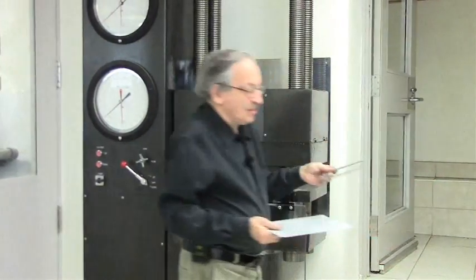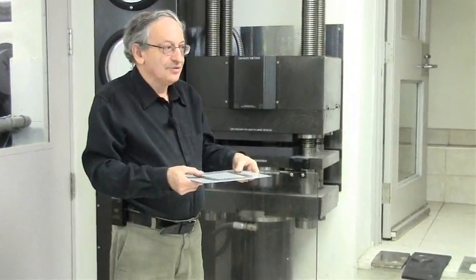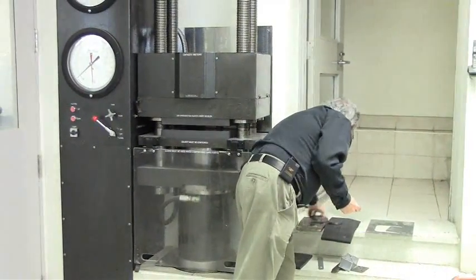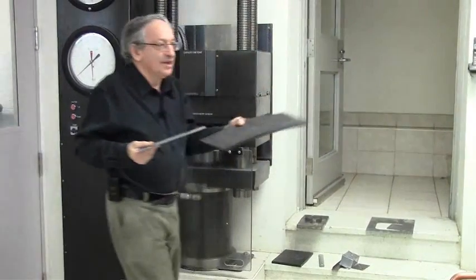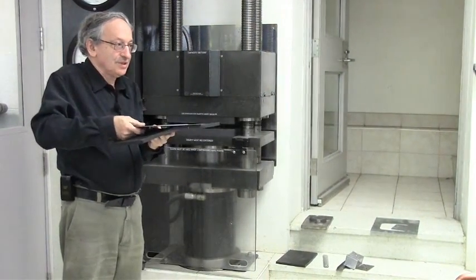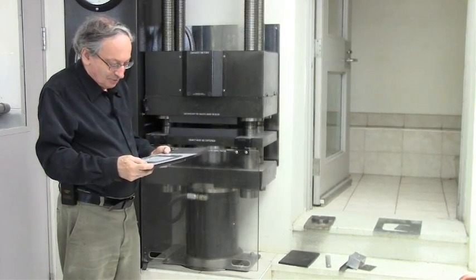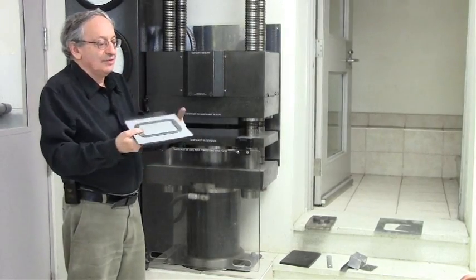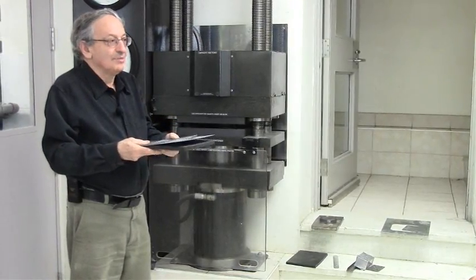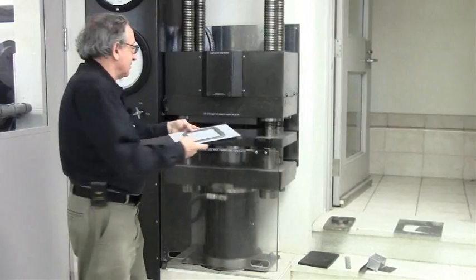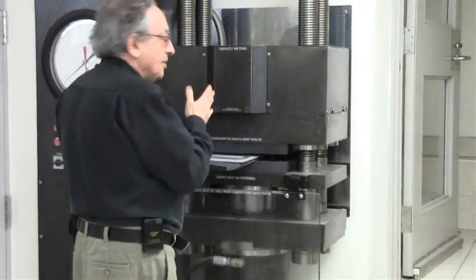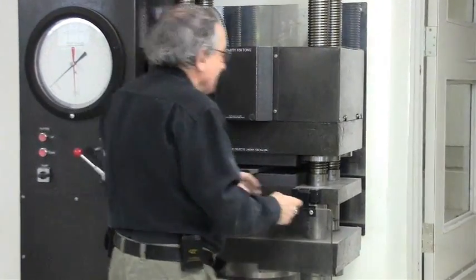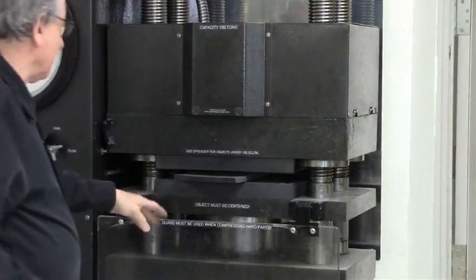So the first way is I just go on the water jet, cut out the shape of the rib I want. Back it up with some material that's a little bit too small. Maybe this is hard rubber. It has to be very hard rubber or very hard polyurethane, which is the best. But even this is a little bit too small, but anyway, that's what we have. So you line it up, and then there's no alignment, it just press up all the material. And put it in. It's important to put it in the middle of the press, because you don't want to try to bend the press. Because it's sheet metal, you can get away without the guard.